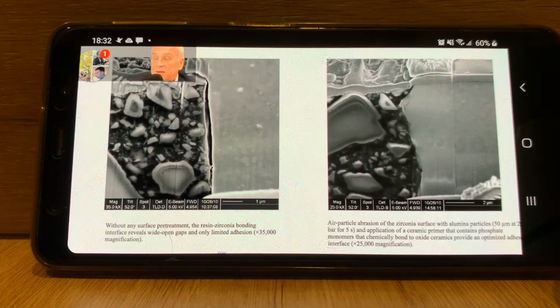Here's an illustration of this. This is from Blatz in the Journal of Dental Research, and you can see on the left side where the zirconia surface has not been pre-treated either by air abrasion or the MDP. You can see that there's no bonding between the composite and the zirconium surface. There's a gap formation. Whereas on the right, it has been pre-treated with both of those, and you can see an intimate bonding between the two materials.